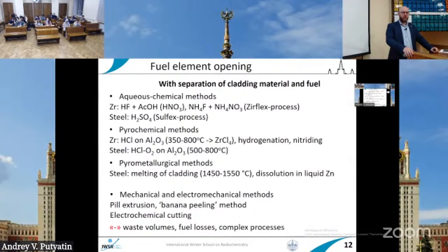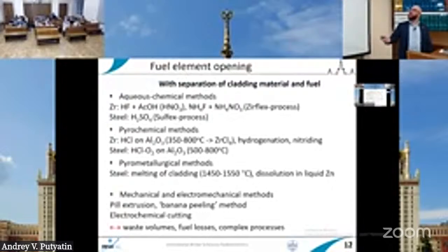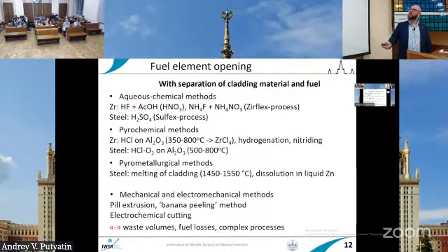To do this, we can again use different techniques: selective separation and dissolution of spent nuclear fuel and cladding. For example, like here, with steel, testing found that steel cladding can be dissolved selectively under these conditions and removed from the nuclear fuel. Another approach is the dissolution of the cladding in liquid zinc during pyrochemical separation.